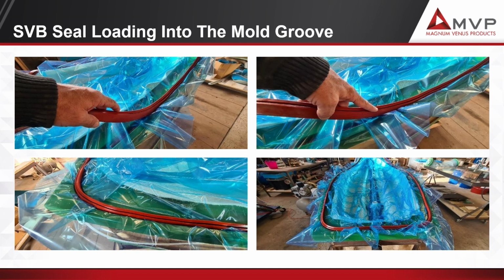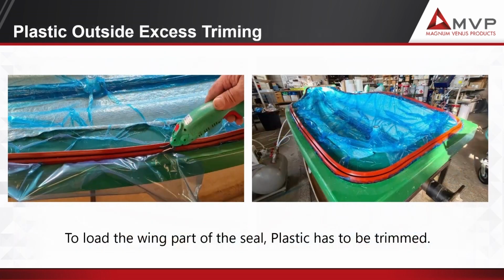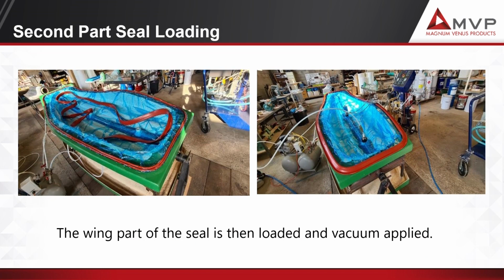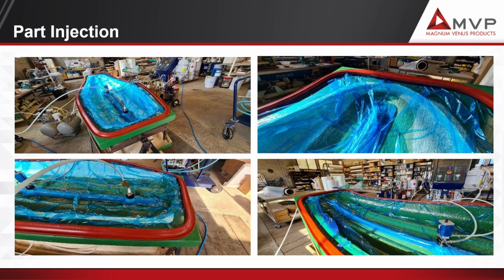So that's the way we work. We load the plastic bag. We don't care anymore about the folds. Folds are not a problem anymore. We load the bag. We are able at this time to apply the vacuum in the middle, but of course we leak. We trim out the excess of plastic. Then we come with the second part of the seal, sorry. We apply the vacuum. And the part we inject like yesterday, we inject the part in 5 minutes, and it's 1 hour's gel time. So during 1 hour, if you have any leak, all the air will come on the part, which we don't have.